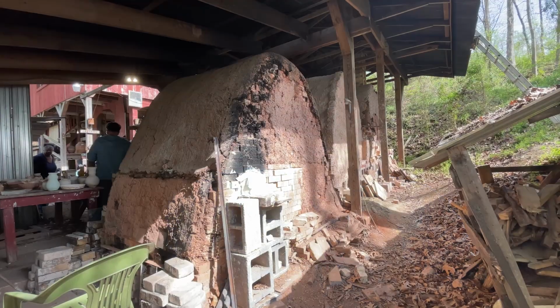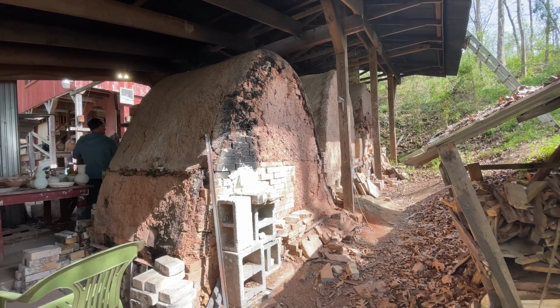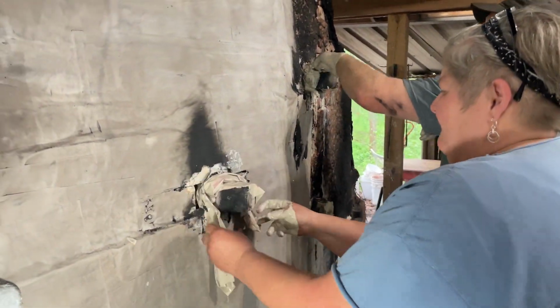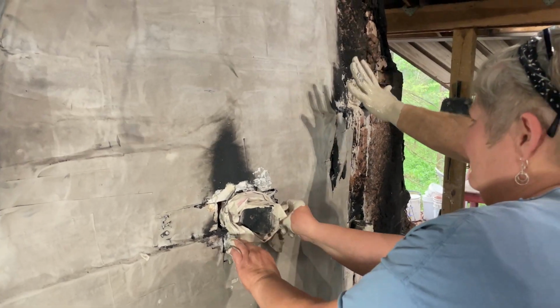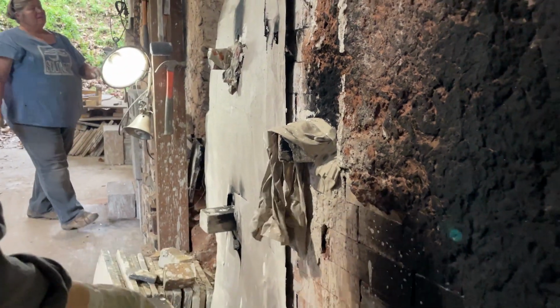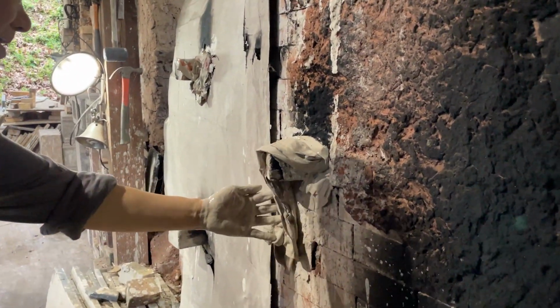Different kilns fire for different amounts of time. This style of kiln, called Noborigama, which is a climbing kiln, it climbs up a hill and has 3 chambers, is an extremely efficient kiln in terms of a wood kiln. At the end of the firing, we seal up the hole, every crack where cold air could come in, because you don't want cold air hitting the pots as they're cooling, or it could actually shatter them.